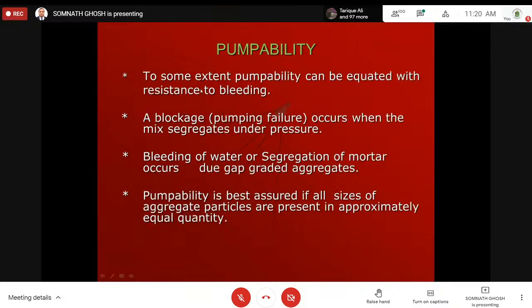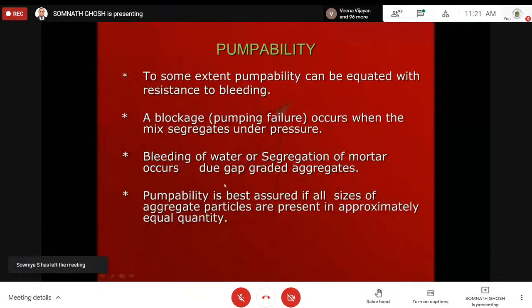Now, pumpability. To some extent, pumpability can be equated to resistance to bleeding. If you can stop bleeding, then the pumpability is better. Blockage and pumping failure occur when the mix segregates under pressure. That means the pressure you have to control. If the pressure is not controlled, then it may happen. Bleeding, segregation of water, all these things due to gaps created between aggregates have to be avoided.